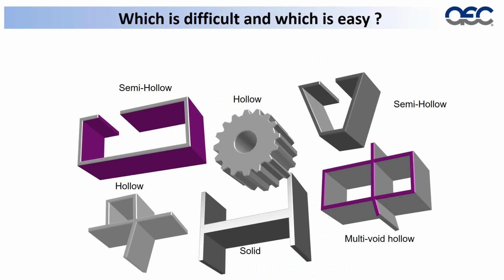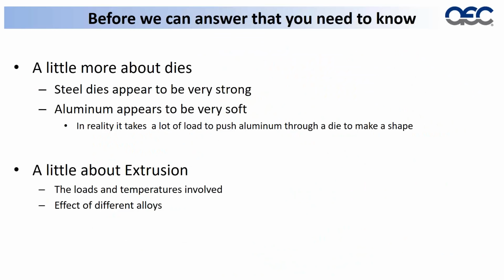But before we can get into determining which is easy and which is the complex ones, we have to know a little bit more about the dies and the problems that come about by extruding some of these non-standard type of shapes. To do that, we have to realize that steel looks really strong and aluminum looks really soft. But the truth is, it takes a lot of pressure to push the aluminum through the die because of the reduction ratio from this very large diameter log to the small, thin, expected shape coming out the other end.